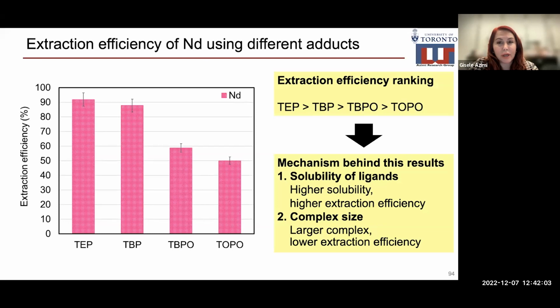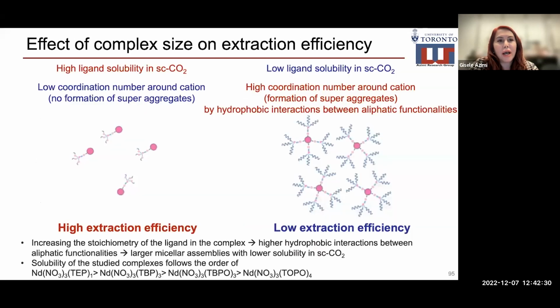We performed the extraction process using supercritical CO2, and we observed highest extraction with TEP, more than TBP, more than TBPO, and more than TOPO. The mechanism behind these results is twofold. One is the solubility of ligand. The higher the solubility, the higher the extraction efficiency. The second is its complex size. The larger the complex, the lower the extraction efficiency. So high ligand solubility in supercritical CO2 and low coordination number around the cation, which results in no formation of superaggregates, results in higher extraction efficiency.